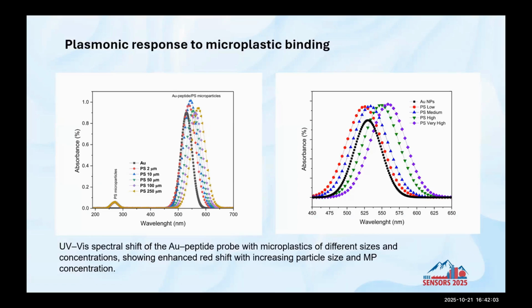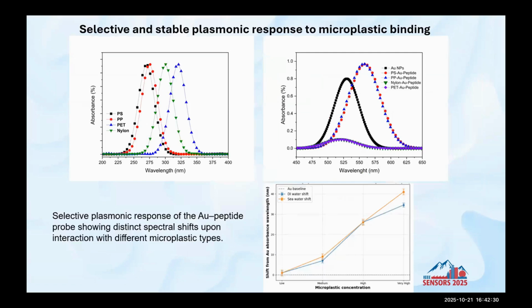And further, we analyzed based on the size. As the size increases, the shift gets to the higher wavelength, and we also analyzed based on different concentrations. By increasing the concentration, it goes higher. It means that larger particles have higher surface area, so more peptide bonding happens, and we can expect a higher shift to the higher wavelength. Higher concentration also provides higher surface area, more bonding happens, and we can expect a higher shift in wavelength.